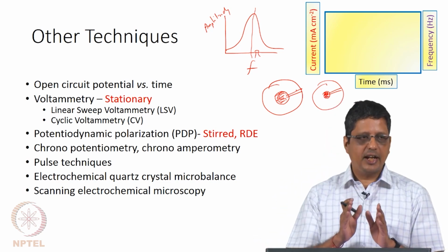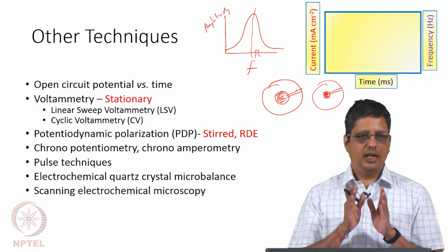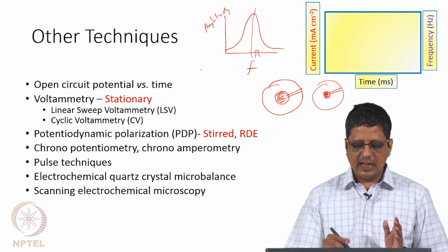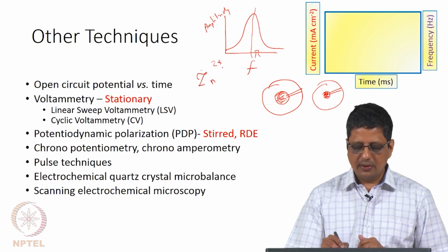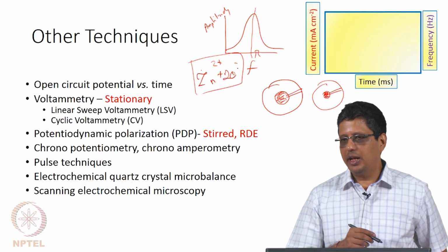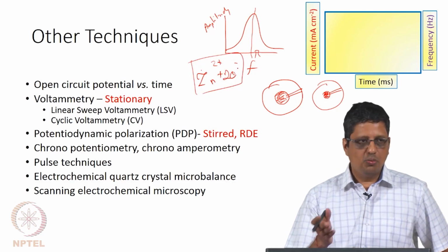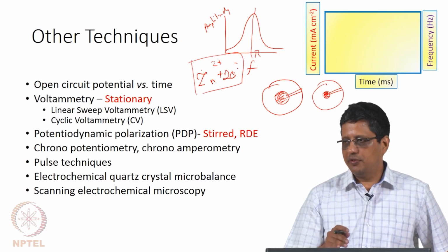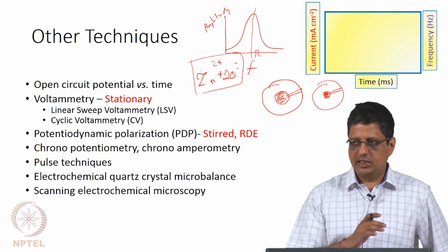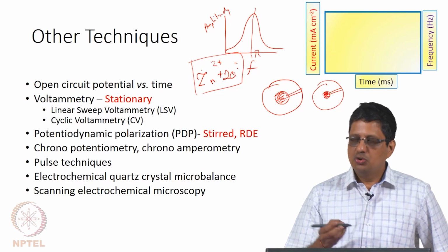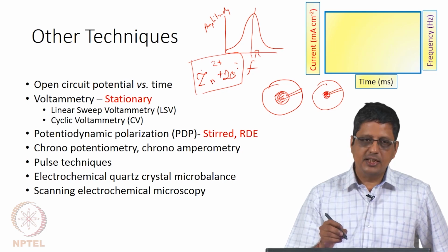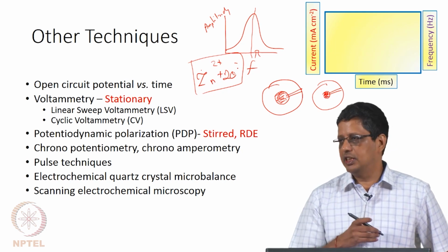There is a constant called Faraday constant which tells 1 mole of electrons will have this much coulombs. Zinc, for example, we expect it to be Zn2+ plus 2 electrons. 1 mole of zinc will give us 2 moles of electrons, or 2 moles of electrons are needed to reduce 1 mole of zinc from the solution. 1 mole of zinc, we know the atomic weight, so we know this much is the mass. So, from the current it is possible to estimate how much zinc should be deposited if all the current has been used for zinc deposition.